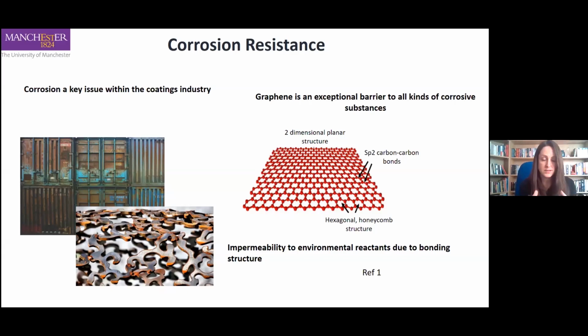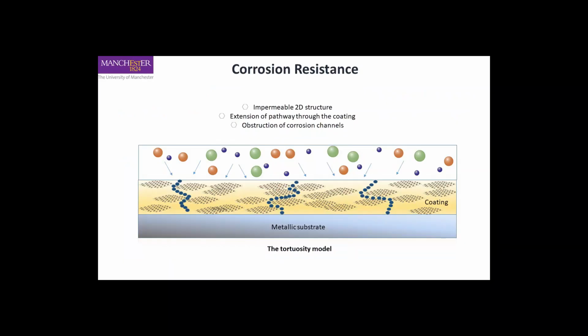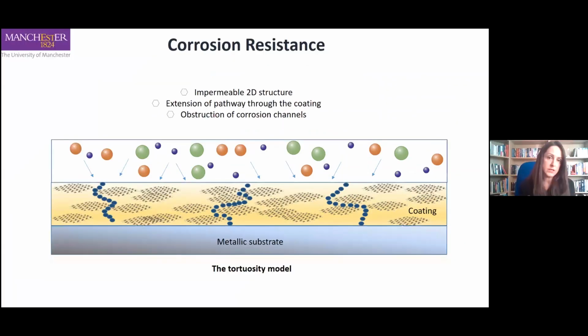If you think about a single layer of graphene on a metal surface, it can completely block diffusion of gases such as oxygen to the metal underneath. And obviously we're not using that sort of graphene in coatings here. We're using more industrial scale, but the principle is still the same. So that big surface area and the 2D nature of graphene makes physical barriers within a coating structure.